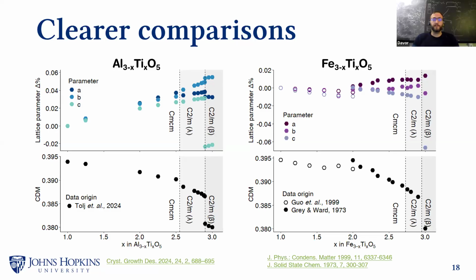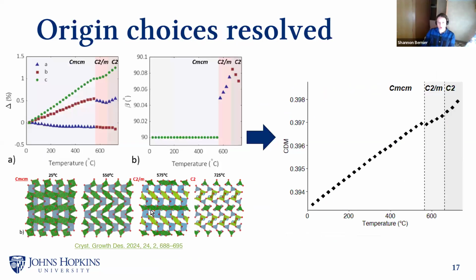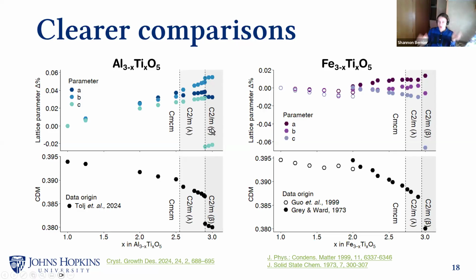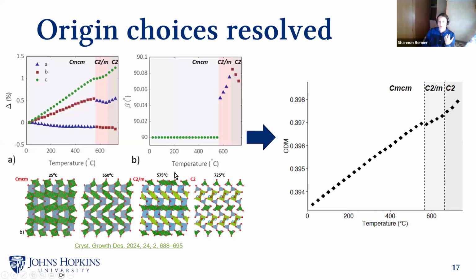In the CDM specifically, we're only considering the lattice parameters, but the structures are truly different. So we're talking about two structures that have this rough structure, but there are different degrees of distortion, specifically in the coordination polyhedra, specifically in the bonding environments. The overall lattice parameters go through a very discontinuous and large change, which is how we know that the atoms have undergone a reconfiguration. But in order to interpret why that happens and its implications for the material's properties, you would go back and look at the specific structures, which both look roughly like this because they're both the same space group, but they have different amounts of distortion in the individual bonding environments of the individual atoms.